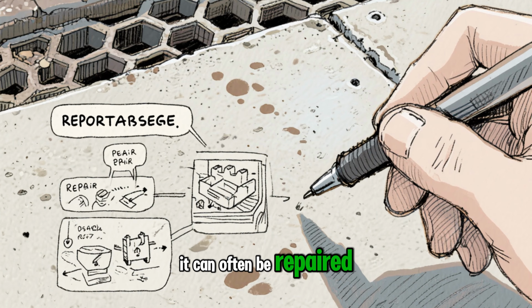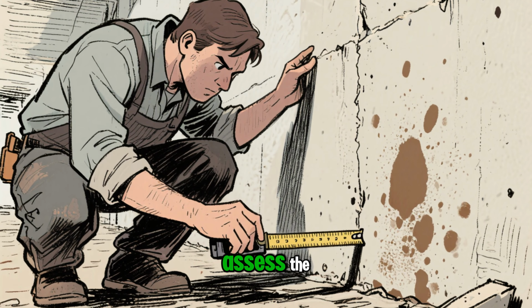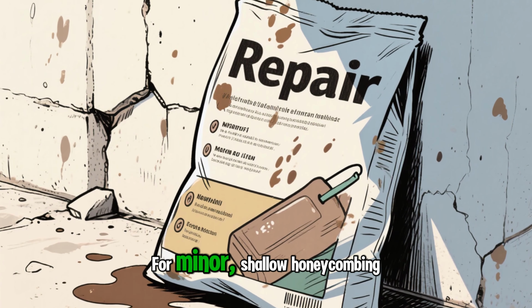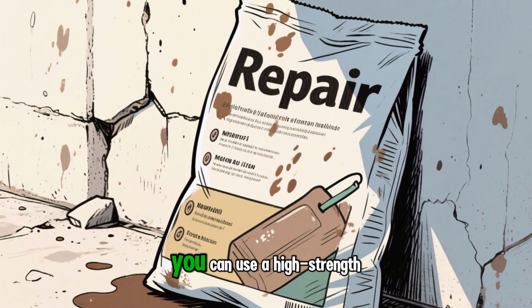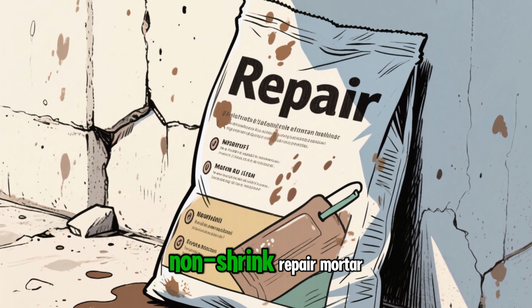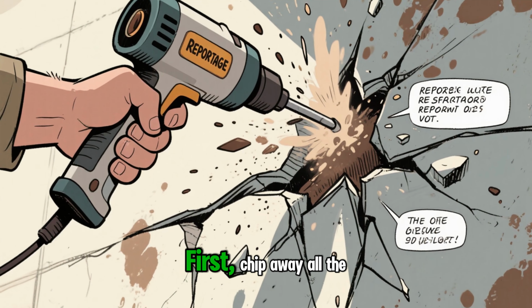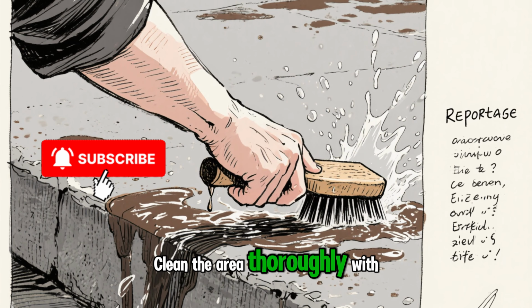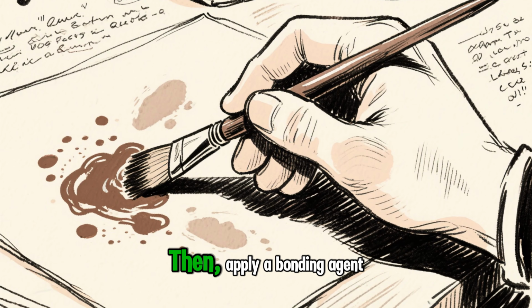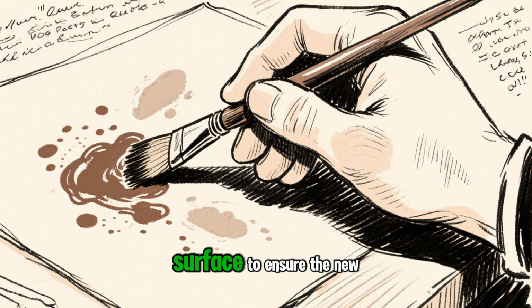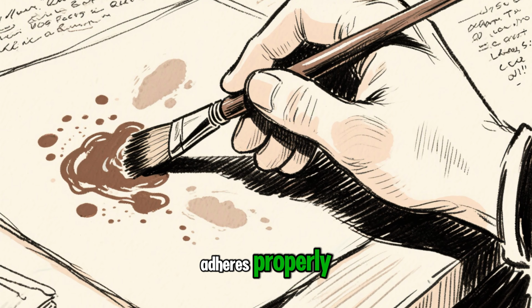But what if you've already found honeycombing? Don't panic. It can often be repaired. The first step is to assess the extent of the damage. For minor, shallow honeycombing, you can use a high-strength, non-shrink repair mortar. First, chip away all the loose, weak concrete until you reach a solid base. Clean the area thoroughly with a wire brush and water to remove all dust and debris. Then, apply a bonding agent to the surface to ensure the new mortar adheres properly.